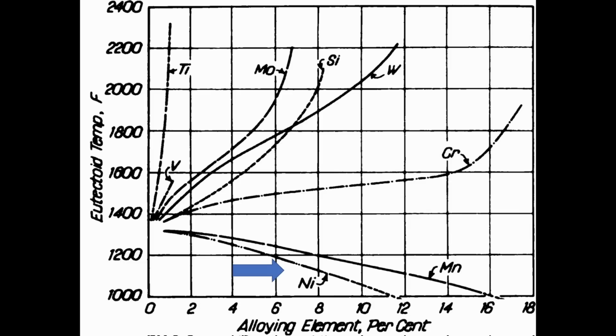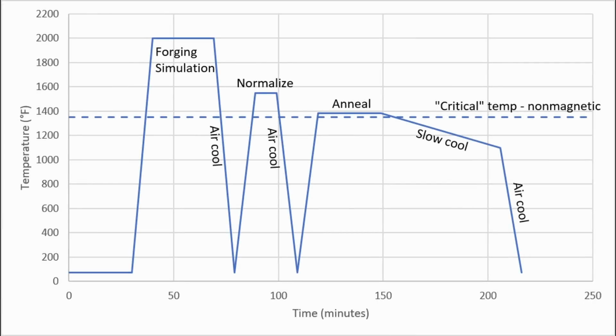Okay, this sounds like a very random thing. Why would this matter? That temperature is also called the critical temperature or the A1 temperature. And this is an issue because when you anneal steel, you heat it up to non-magnetic and you slow cool to soften it. It doesn't start transforming to the soft phases until it gets below the critical temperature. And when that critical temperature is very low, it becomes extremely difficult to anneal the steel at all.